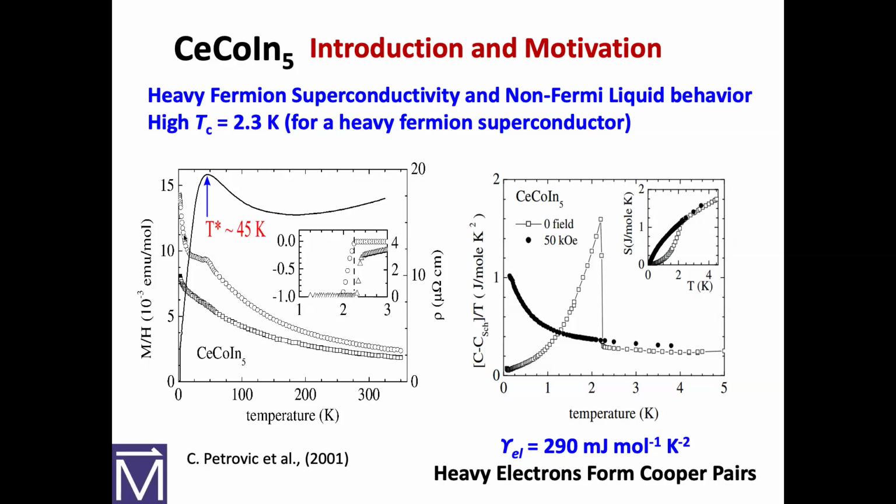And in the cuprates for many, many years, it was a red herring, because we knew there was this structural tipping transition that happened at low temperature, and we were able to determine it had nothing to do with the superconductivity. So typically, I think in general, structural transitions are often not associated with Tc in many materials. The superconducting transition is typically second order, unless you're in a magnetic field, then you can be first order, sorry.